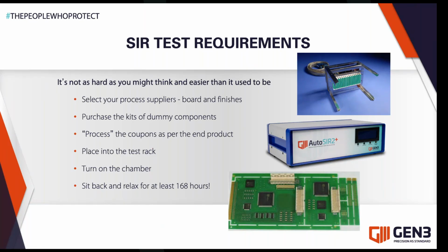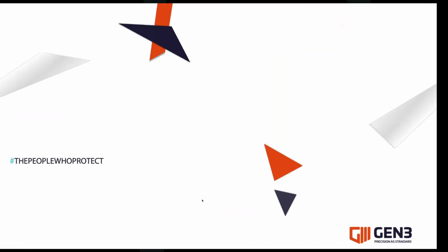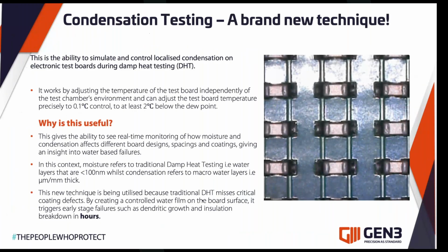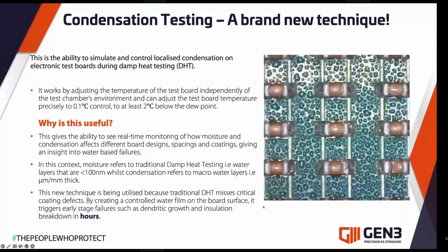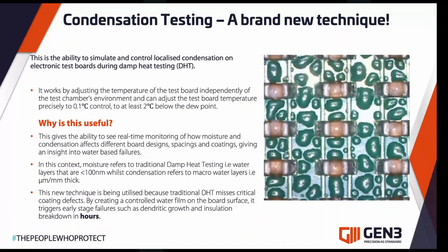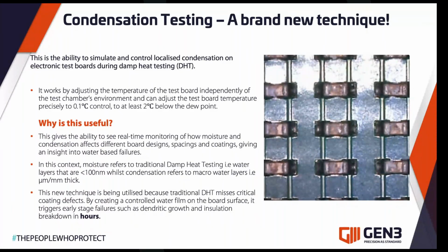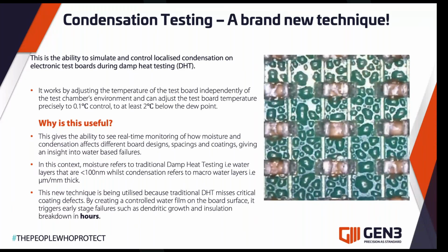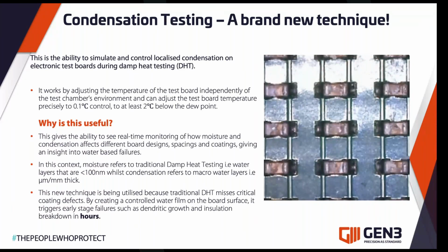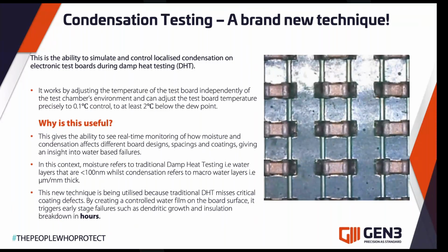Moving forward, there are new advancements in technology and ways of doing SIR, and we're going to talk about a brand new technique that's been developed recently, and hopefully this video will play whilst I'm showcasing. This is a new technique that we've been working on, which is condensation testing. Condensation testing is the ability to simulate and control localized condensation on electronic test boards during damp heat testing. It works by adjusting the temperature of the test board independently of the test chamber's environment, and can adjust the test board temperature precisely to 0.1 degree control to at least 2 degrees below the dew point.